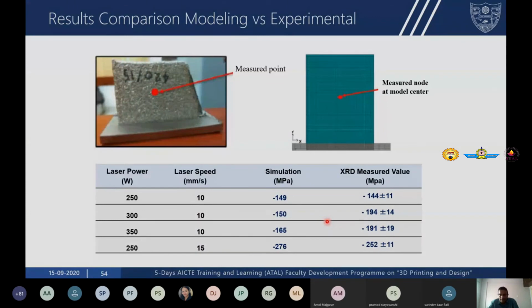So we have deposited an actual thin wall geometry and measured the residual stress using X-ray diffraction at a spot along the thin wall, along the build direction. And this is the thin wall geometry simulated using the finite element model. And this is the same spot where the experimental measurement is carried out and the same spot where the modeling